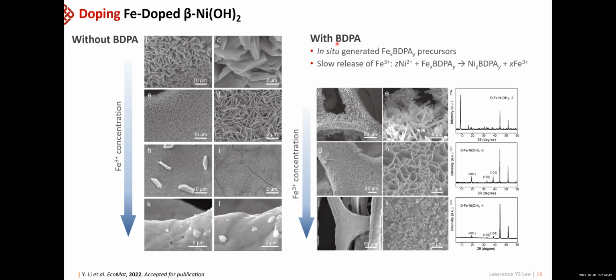So we use this organic molecule to generate the iron BDPA precursor in situ, which will slow down the release rate of iron so that it doesn't make the reaction condition too acidic. Here we show that if you don't have enough iron concentration, you will form nickel BDPA species, so they will form quite different structures. But when we increase the iron concentration to even 10 or 20 millimole, they still form really nice nano-array structures. And when we calculate the iron doping amount, where it was only about 1 atomic percent, we were able to bring it to close to 10%.